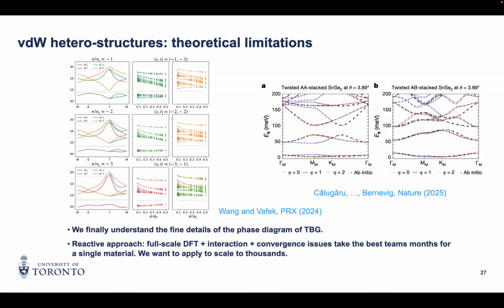So typically, you can also try to get the band structure, so the spectrum as a function of crystal momentum in this big unit cell. But because there are a lot of atoms per unit cell, about a few thousand, this calculation takes a long time. Every one of these plots takes about 3 weeks to run on the cluster, when usually with our code, we expect them to run for, I don't know, 10 minutes or something like that, for regular material with only a few atoms per unit cell. And so we'd like to find a way to predict what's going to happen without spending too much time,